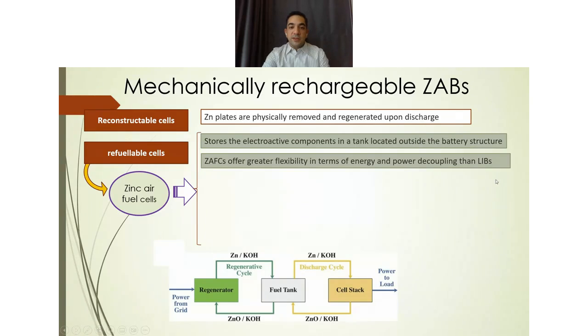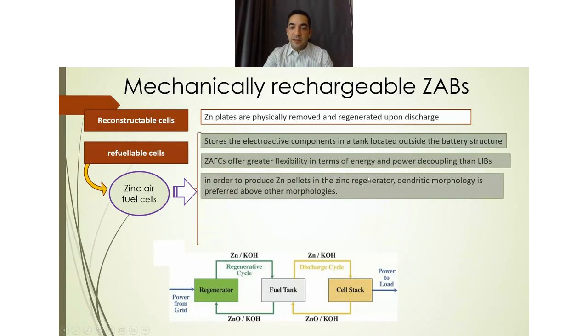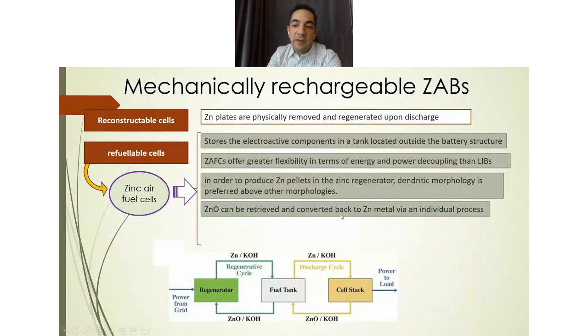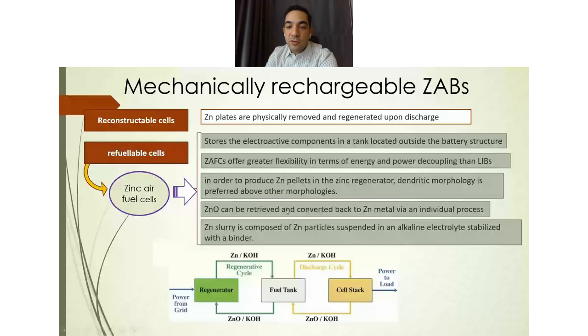And also in order to produce zinc pellets in the zinc regenerator, dendritic morphology is preferred. So for this kind of technology, it is preferred to produce dendritic morphology because in a regeneration unit, you're going to more easily separate the zinc pellets. And also, zinc oxide can be retrieved and converted back to zinc metal via an individual process. And also, the zinc slurry is composed of zinc particles suspended in alkaline electrolyte stabilized with a binder. So this is usually the electrolyte that has been used for zinc fuel cells.